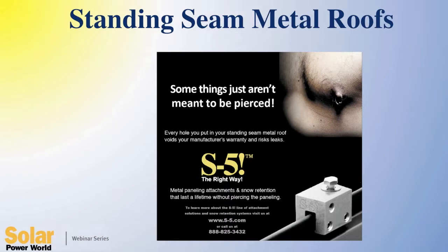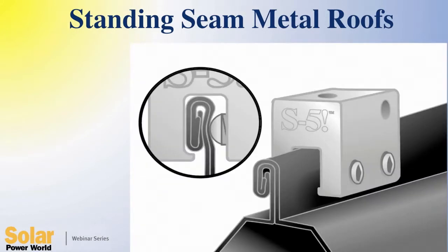So you see, S5 came from the metal roofing industry into the solar industry, not the other way around. That's why it's also recommended by metal roof manufacturers all over the globe and has been successfully used on over 1.5 million roofs. The S5 clamp grips the seam in such a way that it can provide hundreds and even thousands of pounds of holding strength without harming the roof.